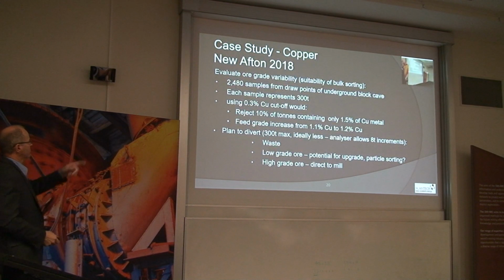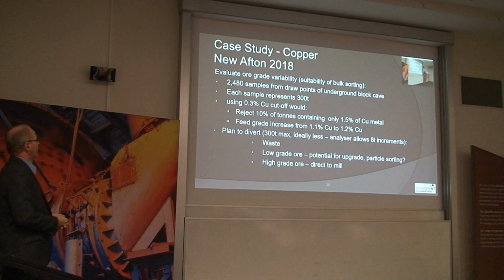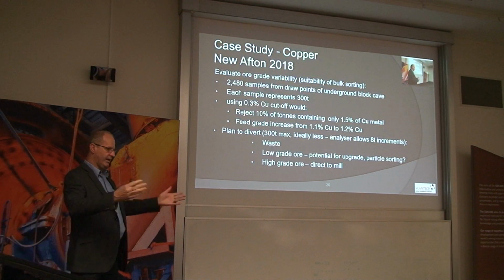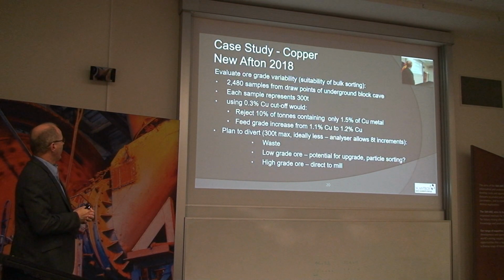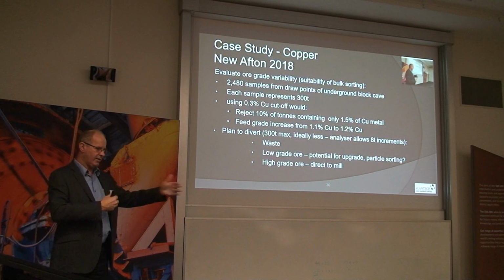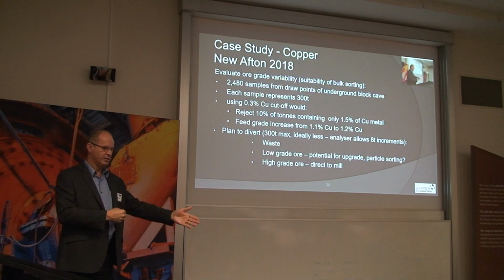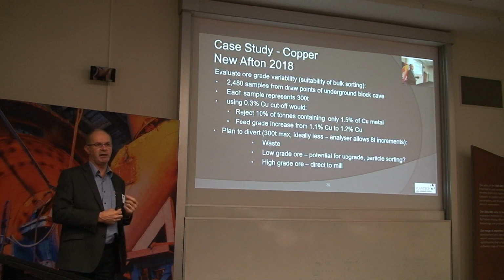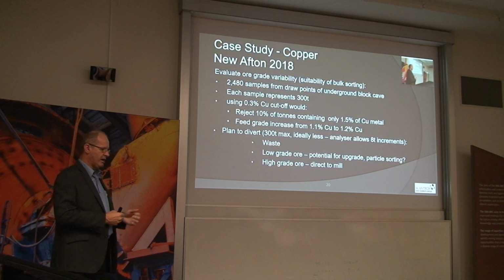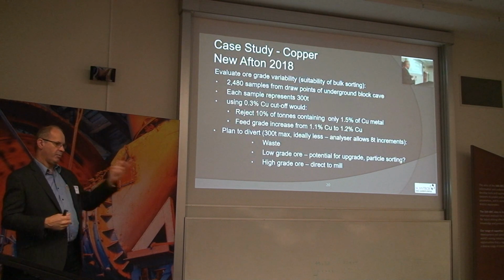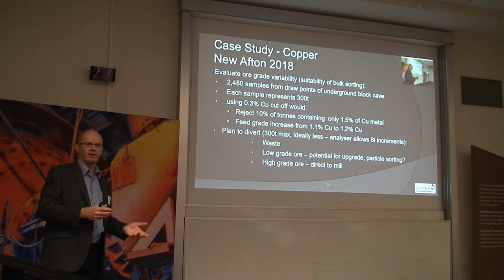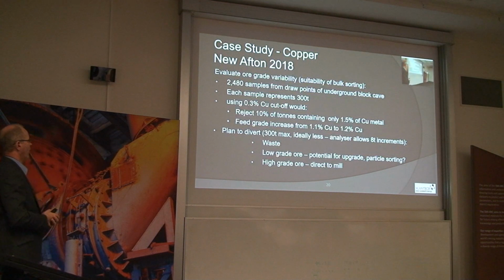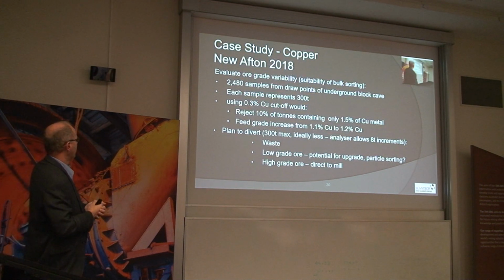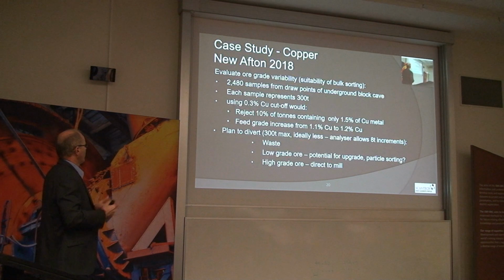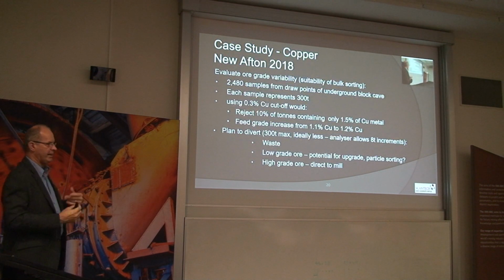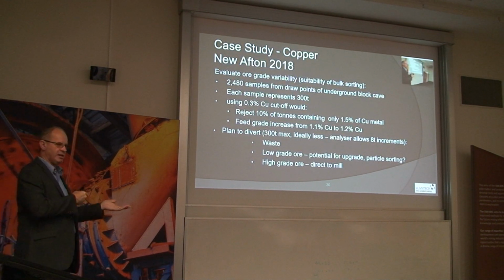So they looked at samples they were taking from draw points. They had nearly 2,500 samples collected over a long period of time. Each sample was collected at the end of a shift for a draw point. So during a shift, 300 tonnes would be mucked out of that draw point into an ore pass, and then the sample would go in and take a not very good sample, but a sample nonetheless. So grab sample, whatever you want to call it, but it gave them some data to consider.